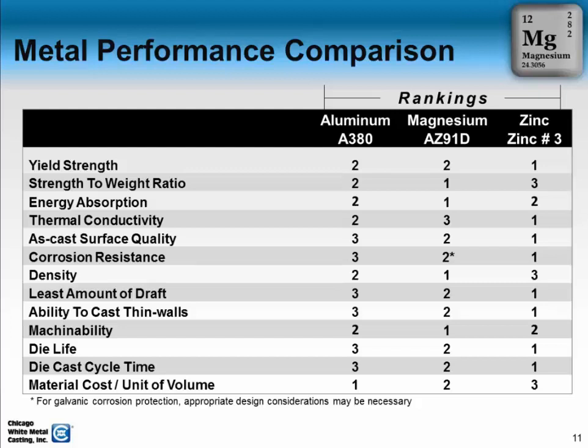What I wanted to point out, though, is looking at that middle column of magnesium, where the number ones are. Where does magnesium outperform both aluminum and zinc? Strength to weight ratio and density are far and away the most important of those things, where magnesium greatly exceeds the other metals. Energy absorption is also rated number 1, and so is machinability, though admittedly we're not looking at magnesium as being that much greater than the others, but it does take less power to machine magnesium than other metals. Other than that, you see a lot of number 2. So for the other properties, magnesium falls well within the normal parameters for other types of structural metals.